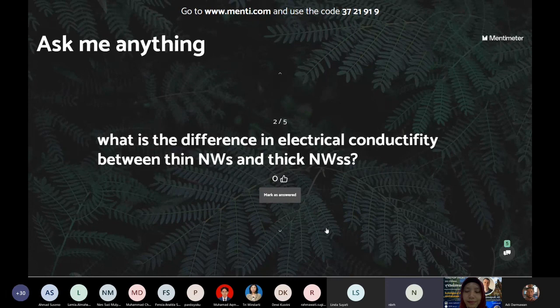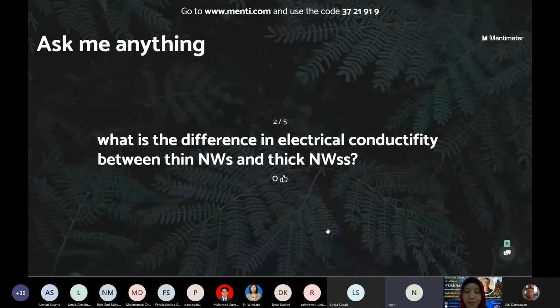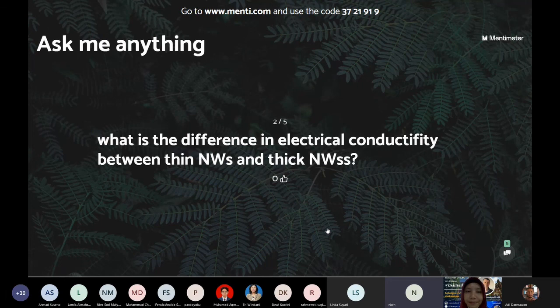If you increase the thickness, eventually the thing just doesn't want to be a nanowire anymore, because it's not really feeling the influence of the template. I don't think any of our nanowires are thicker than about 15-20 nanometers. Occasionally we see thicker objects, but it's always turned out that they are not single nanowires, but more like ropes, where multiple strands of DNA are wrapped around each other and then coated with material.